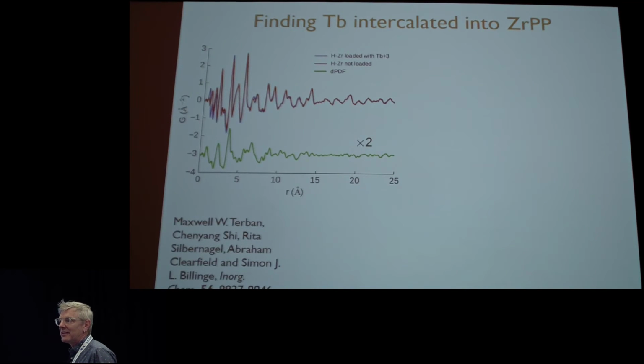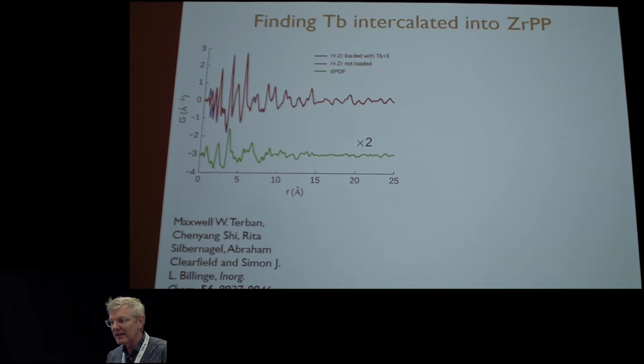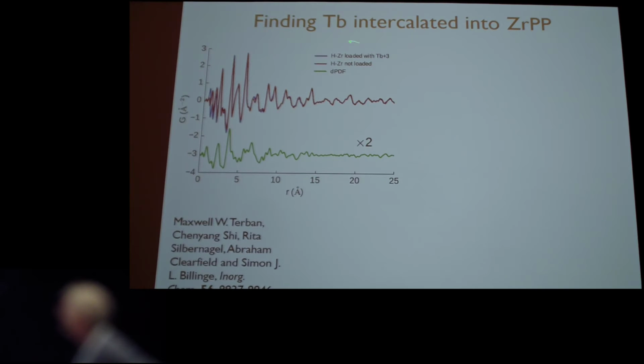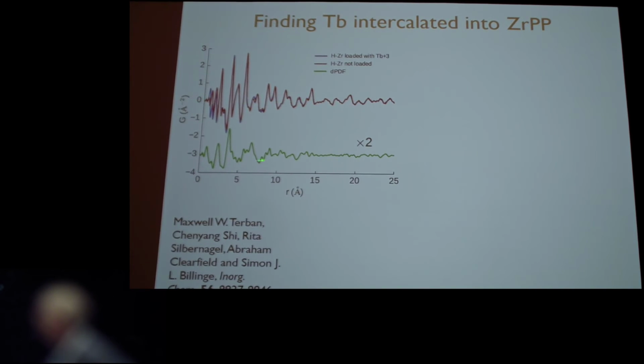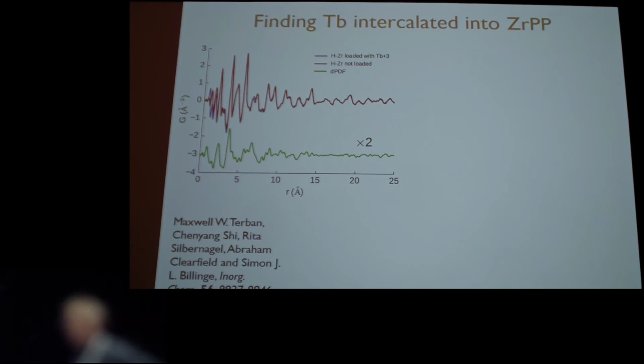But what we really wanted to know is if you put this 3+ ion in, what's the local environment around the 3+ ion? So this is a really challenging experiment because we have a big signal from the framework and then a small signal from it's actually terbium. So these are two PDFs here. One of them is loaded with terbium, and one of them is unloaded. And you can see they're highly reproduced because they're very similar samples. But we take the difference between the red and the blue curve here, and we get the green curve. This has been blown up a little bit. So you can see that there's actually a signal left in the green curve. And that signal is the signal coming from the terbium, or the local environment of the terbium. So it's atomic correlations between terbium and the framework.